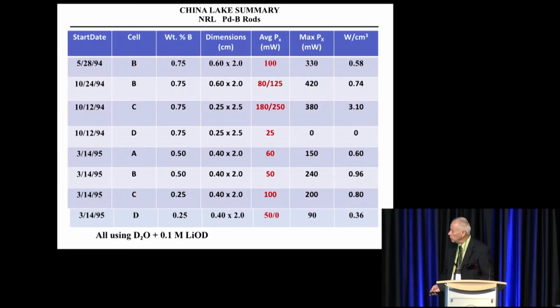Now this is a summary, starting off with the higher weight percents, going to the middle weight percents, going down to 0.25 weight percent, and you could maybe try to see a trend, but I don't see enough of a trend to really make any statement. But I would say in general that the 0.75 weight percent is probably better, and 0.5 is pretty good too. But if anything, I'd say keep it around 0.5 weight percent or 0.75 weight percent. But 0.25 weight percent still gives you an effect.